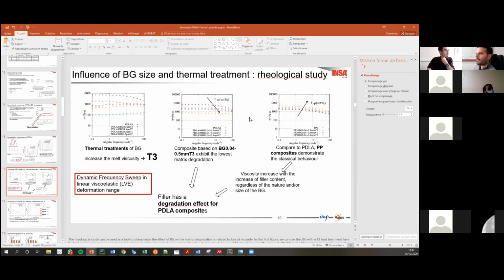but the purpose of using polypropylene was just to compare it in the dynamic frequency sweeps and show that by increasing the filler content, the viscosity of this biocomposite increases, showing the classical behavior and not the same as the bioglass with PLA, where the viscosity decreases due to the degradation.